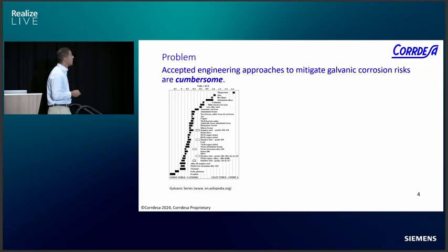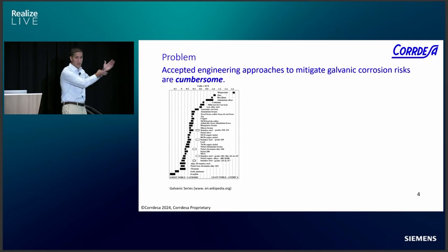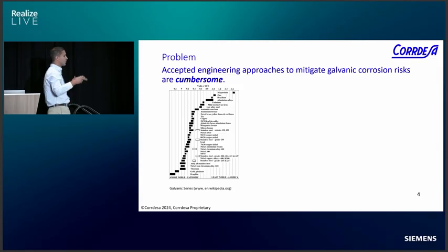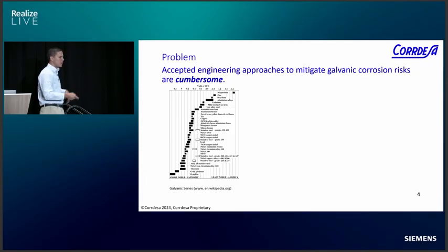This is how we used to tackle the corrosion problem. This is called the galvanic series, and it is based on thermodynamics. Basically what we see here are noble materials and less noble materials. And what this table says, and what we have been using for the last 60 or 70 years, is that the further apart they are, the more corrosion we're going to see. So, for example, these two materials will definitely show lower corrosion than zinc and copper over here, because they are really far apart from each other. But you can see that this becomes really complicated once you start working with complex systems, with multiple materials, multiple phase pairs, and all of that.